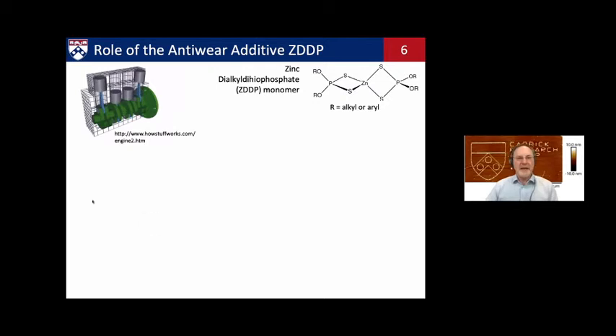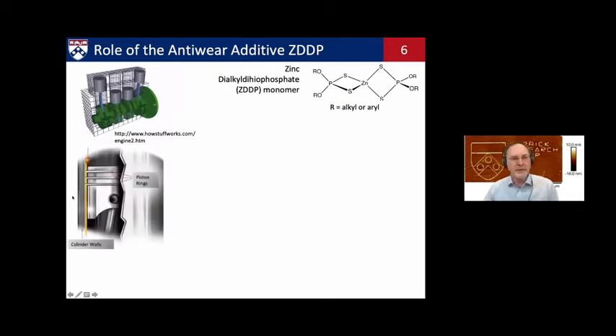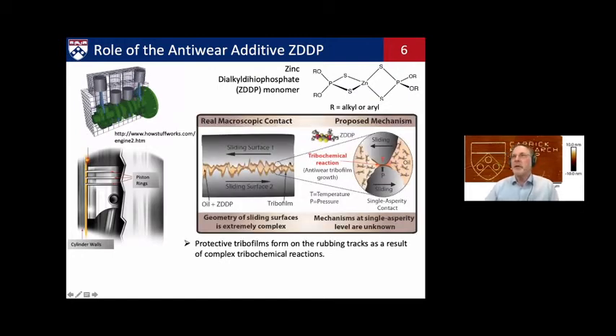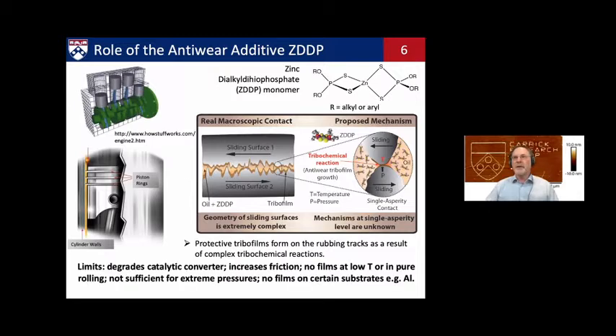ZDDP is this famous additive that works very effectively as an anti-wear agent, also as an antioxidant, and it helps prevent wear at points of severe contact in engines. It's used universally in engine oils, and the way it's known to work is through the breakdown and adsorption of thermal decomposition products of ZDDP that adsorb onto the steel and metal surfaces, and under the action of the contacting stresses, they react with other molecular fragments of ZDDP, and they start to build up a solid-like film that acts as a protective film on the surfaces wherever contact takes place.